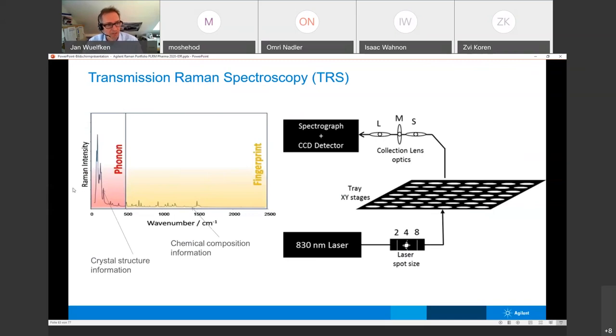But we also get the phonon region. And inside of the phonon region, you get the crystal structure information. So if you have APIs inside of your tablets, which have different polymorph crystallization forms, I'm sure you're struggling, or at least it's not easy to handle, and to see if the right crystal structure is inside of your tablet or not. Because of course, if you dissolve it in your HPLC analysis, the crystal structure is gone.